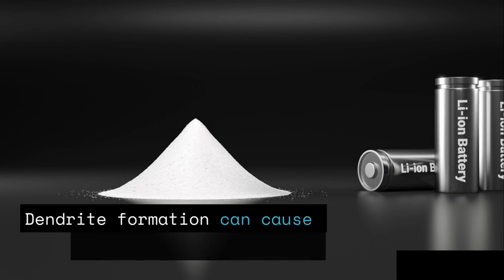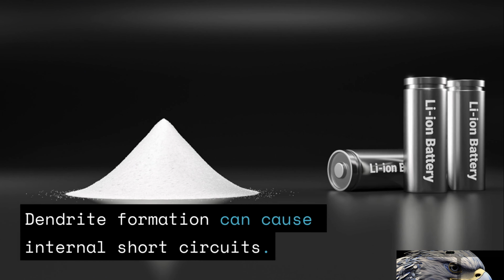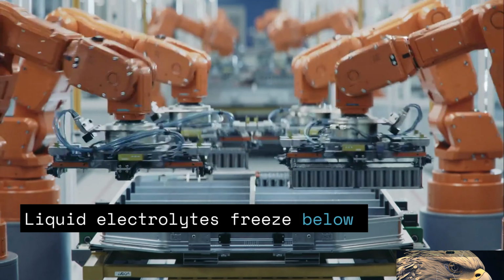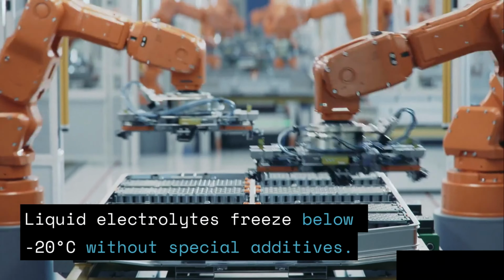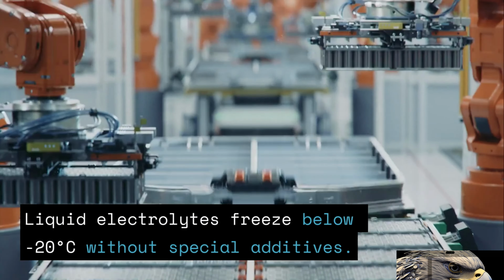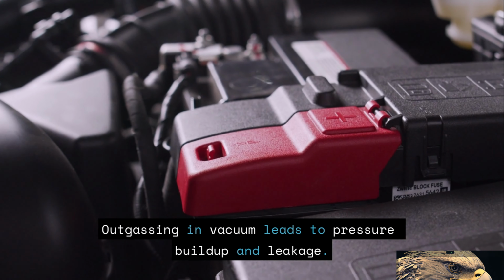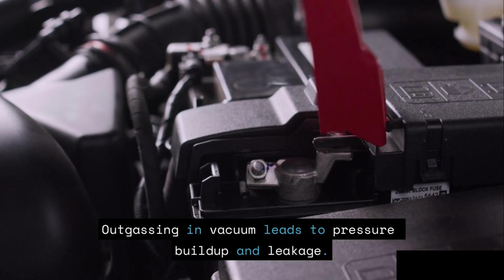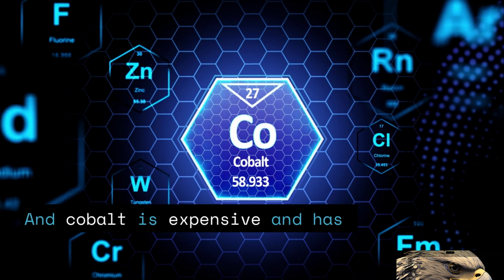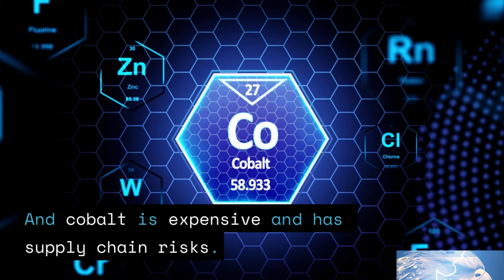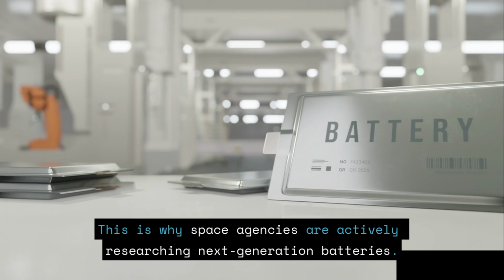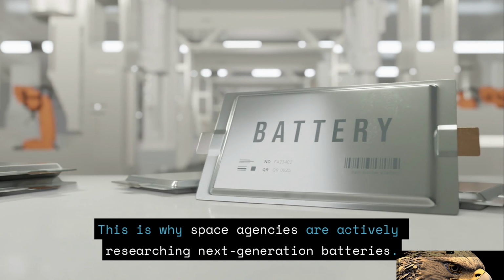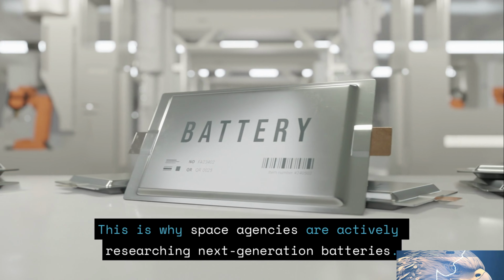Dendrite formation can cause internal short circuits. Liquid electrolytes freeze below -20 degrees Celsius without special additives. Outgassing in vacuum leads to pressure buildup and leakage. And cobalt is expensive and has supply chain risks. This is why space agencies are actively researching next-generation batteries.